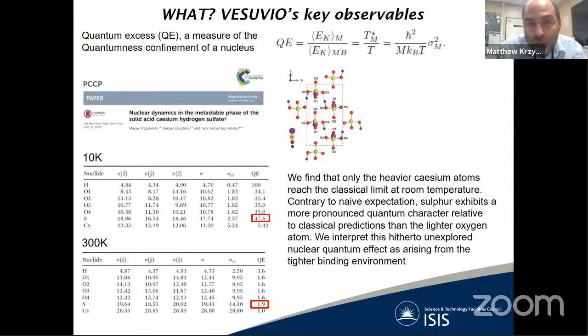materials and give you quite a lot of surprises, because contrary to the naive expectation, nuclei that are much heavier than protons still exhibit a marked magnitude of nuclear quantum effects, as investigated in this example of nuclear dynamics in the metastable phase of the solid acid cesium hydrogen sulfate. In this case, we have measured this quantum excess in an atom-resolved manner using neutron Compton scattering. And we have discovered that in the case of sulfur, the value of the quantum excess is much higher than the value of the quantum excess for the much lighter oxygen atom. So sulfur is in a way much more quantum than oxygen, even at room temperatures.